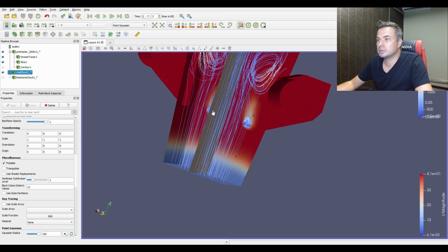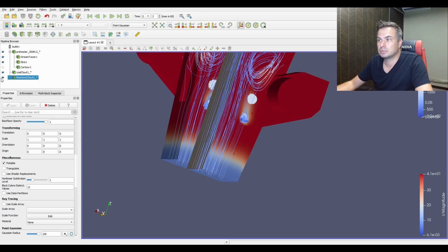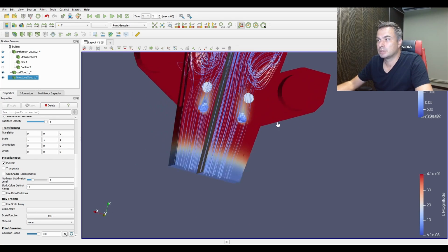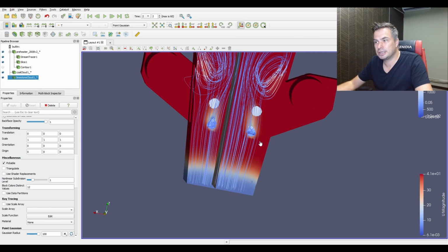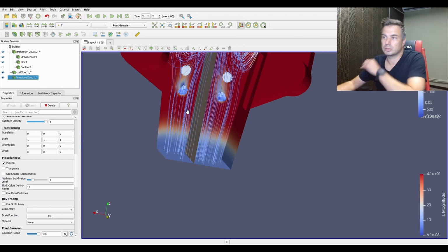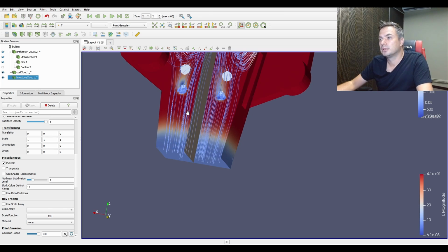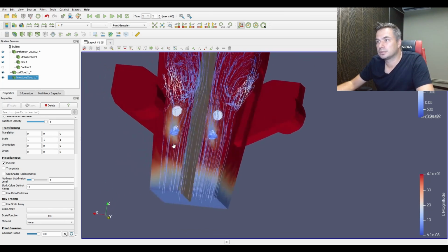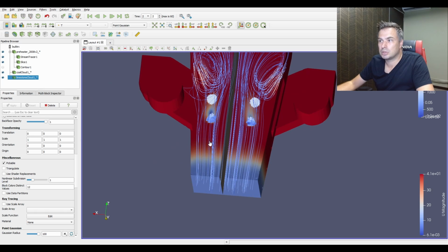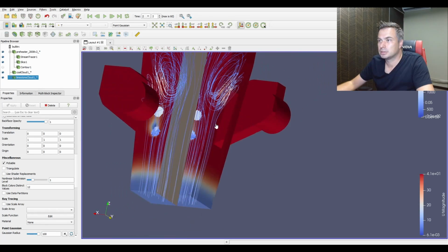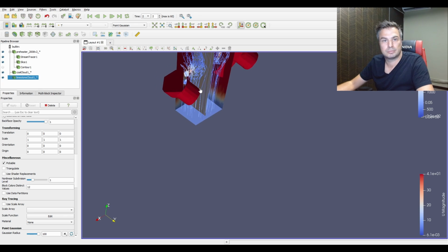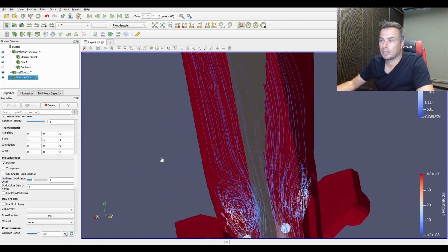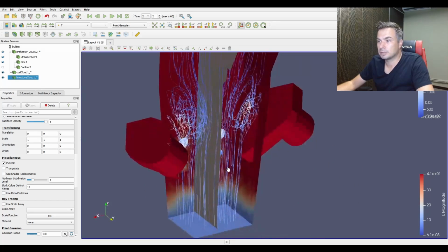What we try and do is move the coal away from the limestone, coming above it, maybe to the sides here. Also try and inject it a bit further into the gas stream, get better mixing of the coal and the oxygen to get better combustion. Try and have a fully developed combustion zone, quickly to calcinate the limestone.